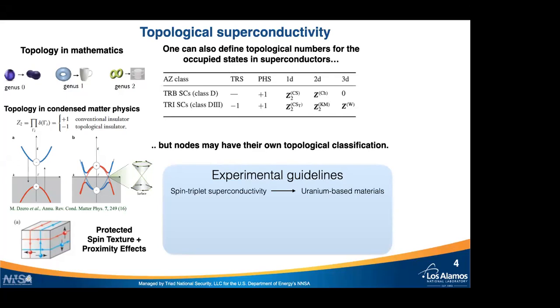But we really need to take a step back to be able in the end to perform the topological classification. We need to know what the superconducting order parameter is. We need to know whether time reversal symmetry is broken. We need to know what the uranium valence is in the material, and we need information on the Fermi surface. So it's a really huge experimental effort, and we're very excited actually to be doing this type of research.